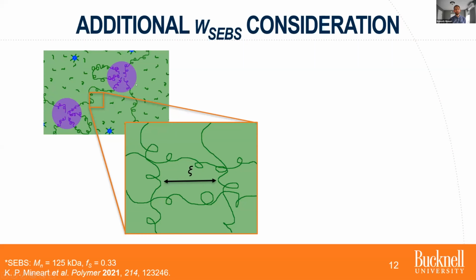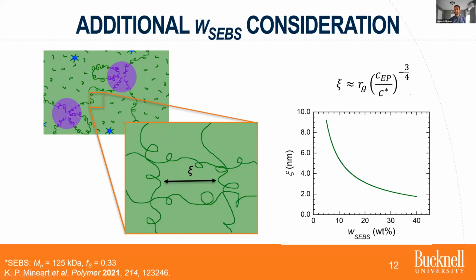In terms of the mesh size, it's very difficult to measure in these systems because of the electron contrast between the other phases, but we can do a calculation based on some scaling theory originally postulated by Pierre-Gilles de Gennes, which defines the mesh size as a combination of the radius of gyration, in our case of the mid-block chains, the overlap concentration of these chains, and the actual concentration of the mid-blocks within the green space. So this is not an overall concentration, but the concentration of ethylene butylene chains within the green matrix.